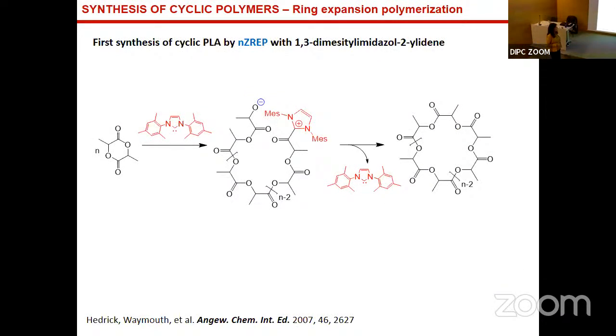This is related to the zwitterionic ring expansion polymerization. This is another technique to generate cyclic polymer, also by this ring expansion. This was demonstrated by Waymouth and Hedrick in 2007. They demonstrated that by using organic catalysts, no metals, this carbene was able to polymerize the lactide and to generate cyclic polylactide. This is a polyester, very important in industry, in packaging, and because it's biodegradable, etc.